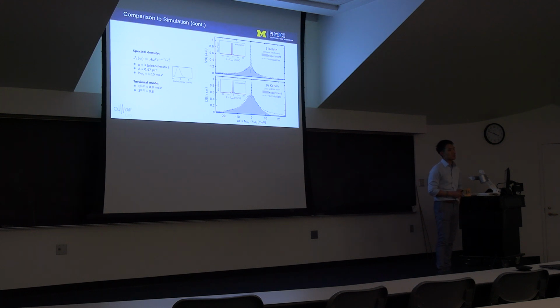and the T1, I forget what you guys call it, but when you vary, I guess it's big T, did you do that also? Did you see a fast decay and a slow decay in that system, or at least a biexponential? No. In fact, it doesn't decay very much because the population times are nanoseconds at least. In fact, they're beyond our stage now. What's the dephasing time? It's over 50 picoseconds.